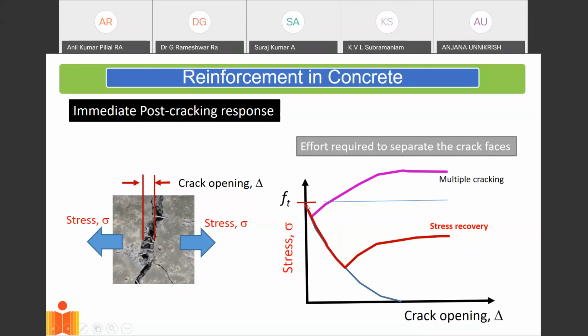FT is where the crack forms, and once the crack forms and as the crack starts widening, the stress that it takes to pull the material apart decreases very rapidly. The minute I start putting some fibers in there, the fibers will arrest the crack, and at low dosage of fibers, I get some stress recovery. Basically, the fibers are able to hold the crack and actually give you some resistance as the crack is being opened. And if I increase the fiber dosage, I can even get to the point where the resistance coming from the fibers exceeds the strength of the material. And when that happens, I get multiple cracking. So instead of having one big crack, I get 50 smaller cracks that are formed in the material.